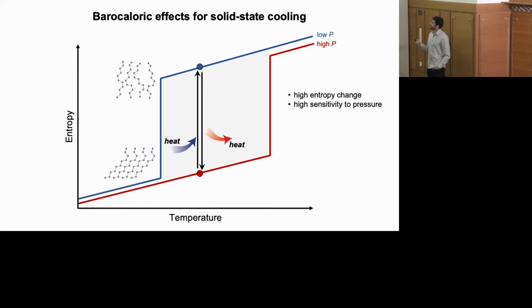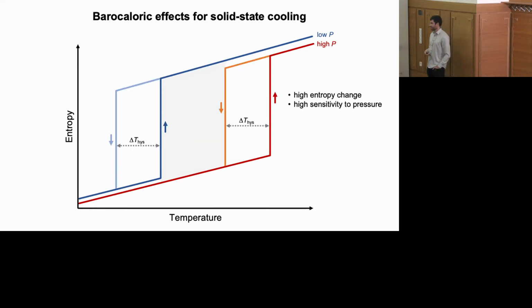So you want a material that undergoes a transition with a large entropy change that's very sensitive to pressure. You also have to consider the reversibility of these phase transitions. Typical first order phase transitions in materials do not look just like I drew them here, where they're infinitely sharp and completely reversible, but they often have a degree of thermal hysteresis associated with them.